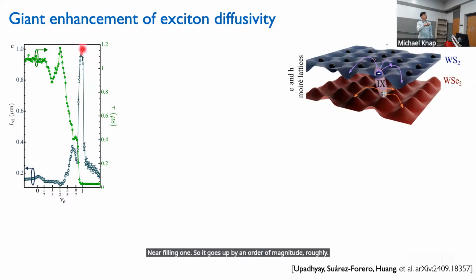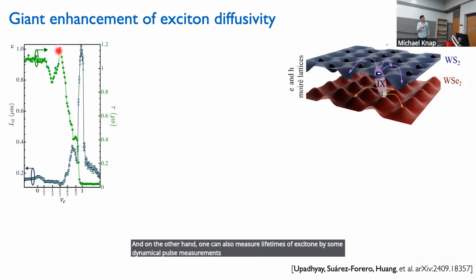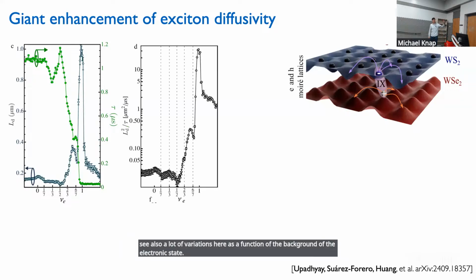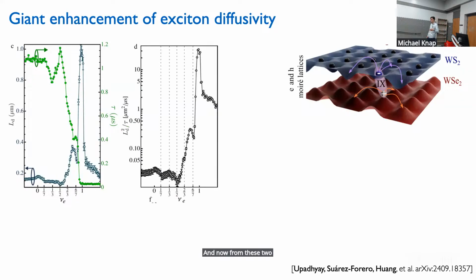On the other hand, one can also measure lifetimes of excitons by dynamical pulsed measurements. This is the green curve. And you see also a lot of variations here as a function of the background of the electronic state. Now, from these two quantities, length and time scale, one can extract a diffusivity: dividing the length squared by time gives a mobility or diffusivity for the system.